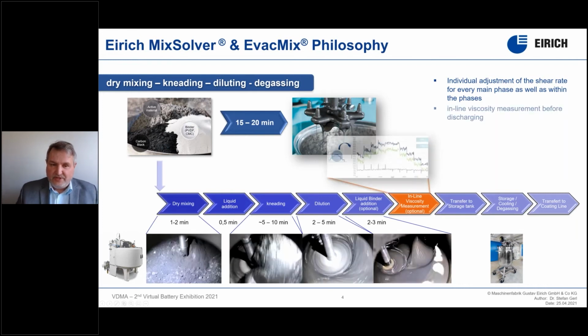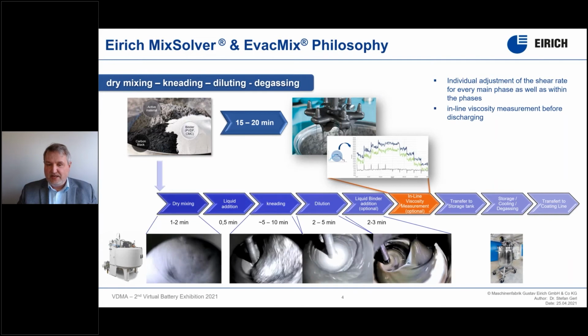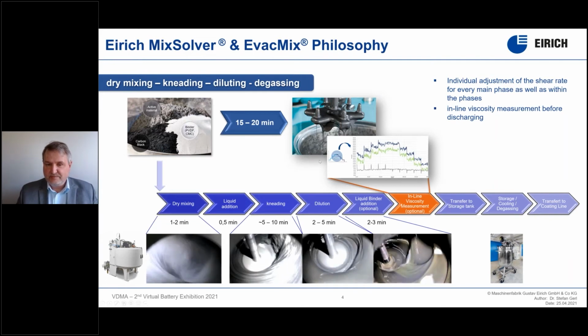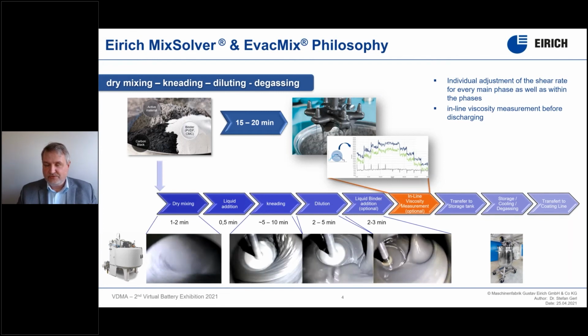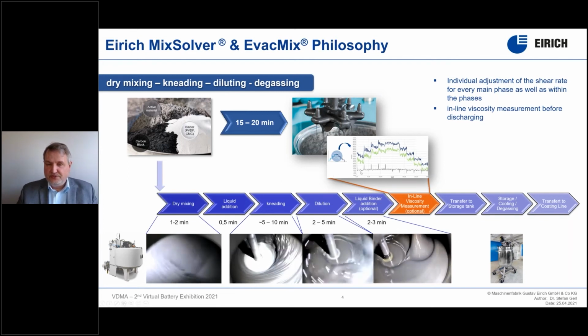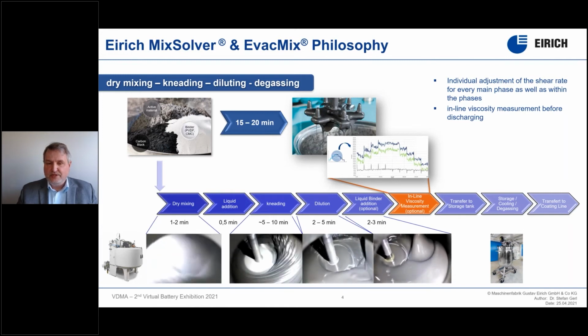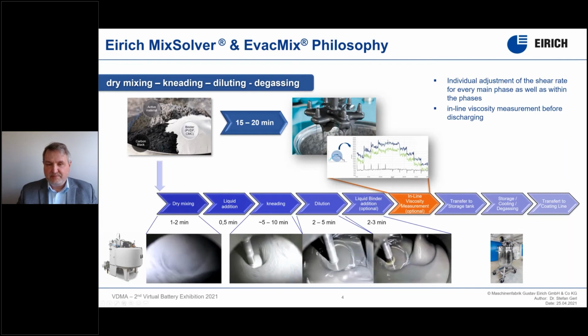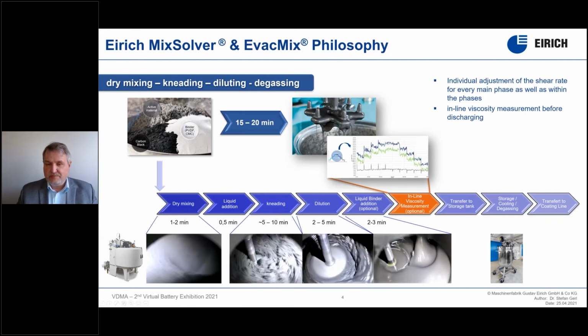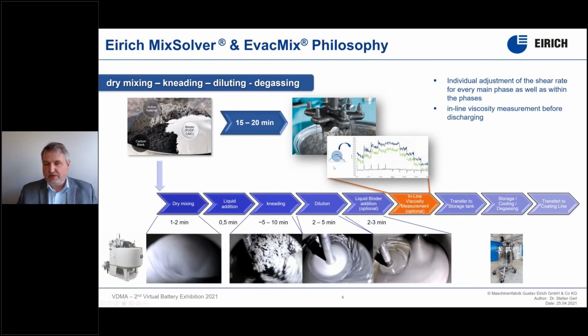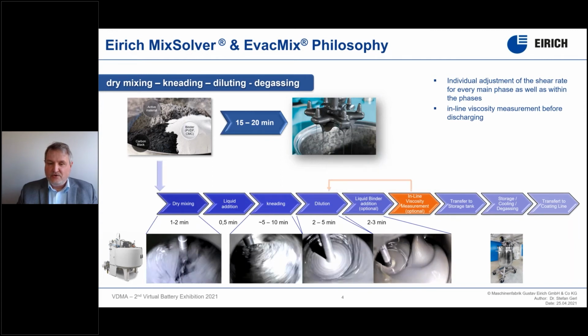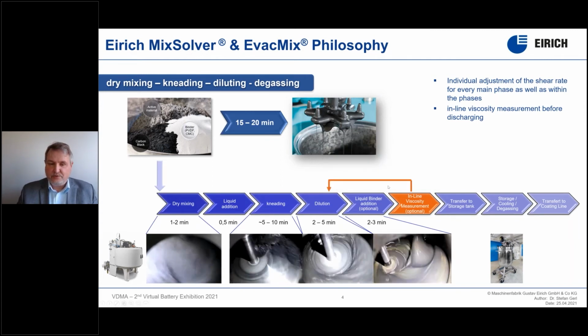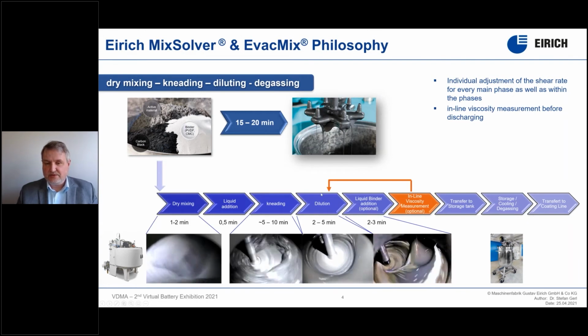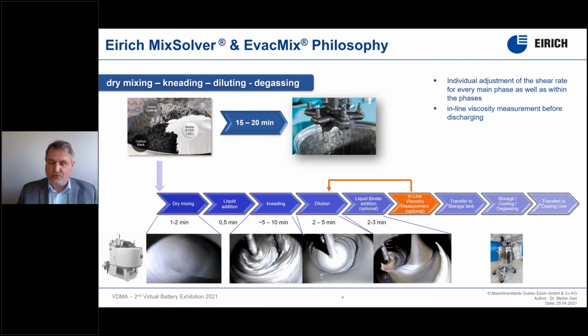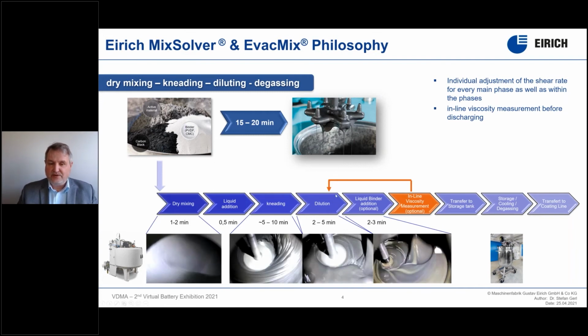And we then have the ability with our system to make an inline viscosity measurement before we discharge the slurry into the following transfer system. This is a special measuring procedure, which allows us to change the rotor speed in different steps, and we can ramp it up and ramp it down like a rheometer. And by this, we measure the motor power absorption, the torque, and can calculate the viscosity. Of course, this viscosity measurement need not be at the final end. It could also be part of the dilution phase in between at higher concentrations, and would by this allow us to control and to adapt the amount of liquid added in the final phase to control slurry quality.